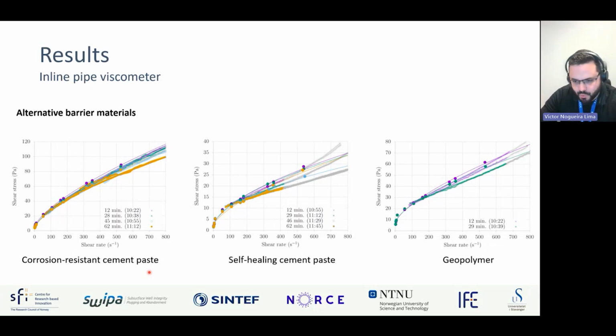And as you can see, once again, over here in these curves, we still have a very nice agreement between the pipe viscometer and the FANN 35 measurements when we compare the pipe viscometer and the rotary viscometer.